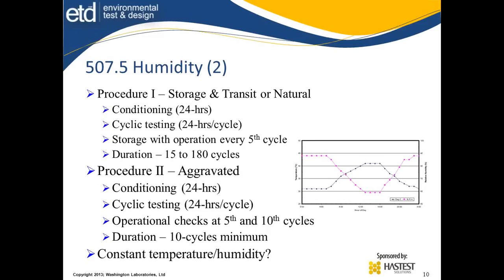Everybody says, what? I didn't read that. Well, that's what the standard says, and the life cycle program calls for that. Any of these tests, the minimum time we see is 15 days, but yet all of us are seeing 10-day or 3-day humidity exposure periods called out all the time for these durations. Procedure 2 is an aggravated cycle, which calls for the conditioning like that.